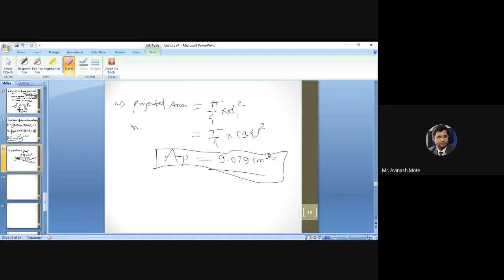It is quite lengthy and complex, since we need the dimensions of the gating system. So rather than going deep into those dimensions, we use an allowance, an extra area in terms of additional allowance, which is 10% of the projected area.